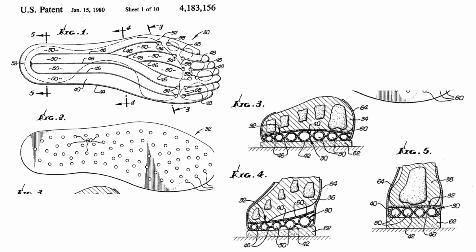Therefore, the insole, including the critical areas along the edges of the weld areas, is subjected to a potentially very destructive accumulation of peak stress and stress reversals. The selected materials provide the best possible endurance under these conditions. Also, and equally important, the design configurations of Figs 1 to 31 are such as to minimize stress concentrations and minimize the overall stress levels on the welds, even at a maximum design 50 psi condition, so as to give the insole long in-service life in excess of the life of the shoe.